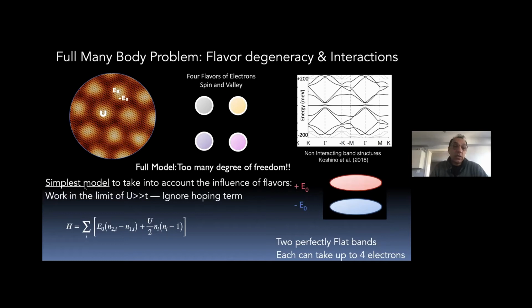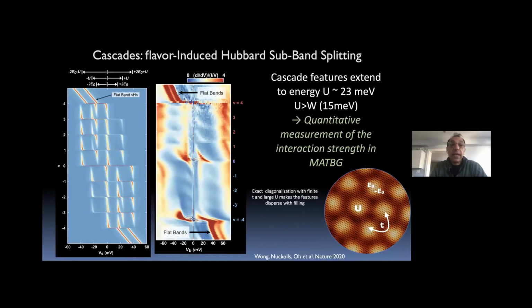So what you want to do in order to make progress trying to understand our results is to make some simple assumptions, like let's take the infinite U limit of this system where you have almost 0 hopping. And if you ignore the hopping term, you can begin to understand what the spectroscopic measurements are by simulating the electron addition and removal spectra of that infinite U Hubbard model. So on the left are the calculations that come out of such a simple model. And on the right, I have the experimental results. These 2 lines just represent the 2 levels of the flat band. And then you see a successive number of features in between. This is just a quantum dot type of model.